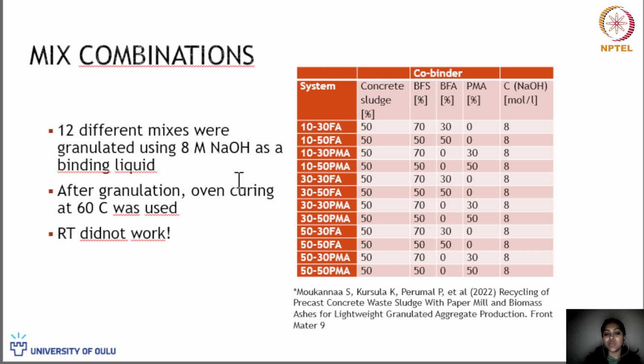So 12 different mixes were granulated with an 8 molar sodium hydroxide solution. There is no sodium silicate added here, which is termed to be a highly non-environmentally friendly activator, so we avoided the sodium silicate. And after granulation, these materials are cured in an oven at 60 degrees Celsius. Room temperature we tried, but it didn't work with this material. So we went for 60-degree oven curing.